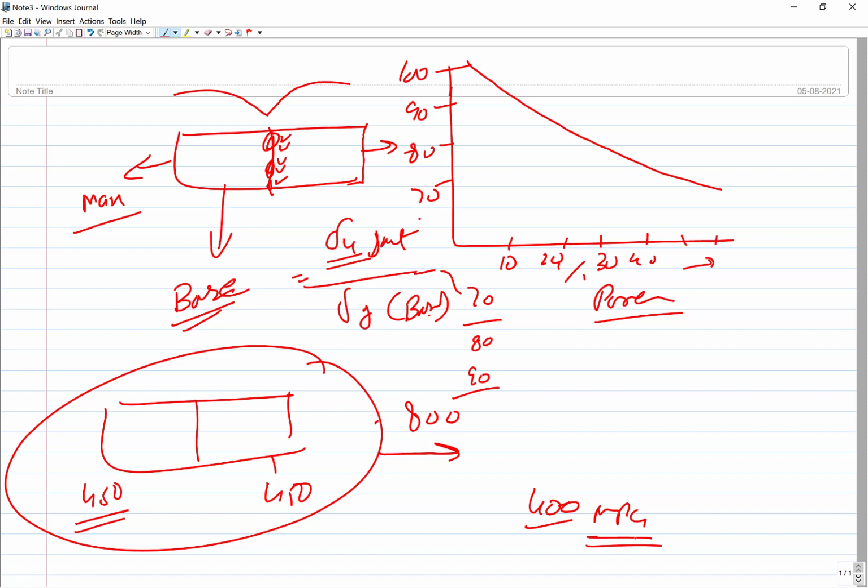So that's the third approach where, wherever diffusion bonding is performed, if the joint is free from discontinuities, you may get a joint strength as good as that of the base metal, otherwise it can be compromised significantly. The second is that the base metal properties are also compromised. Okay, coming to the deformation, we are now left with two approaches, deformation and fusion.